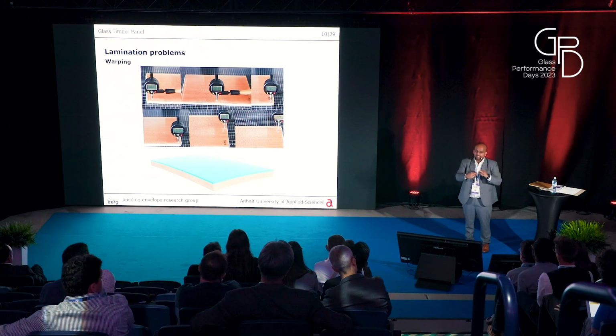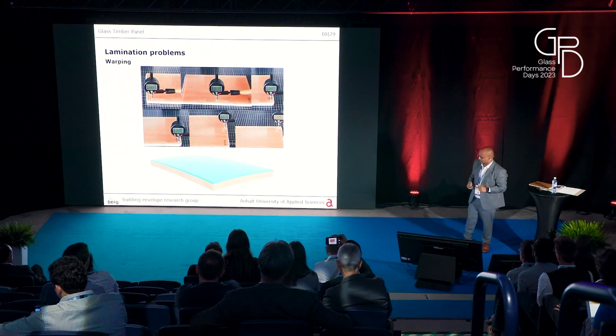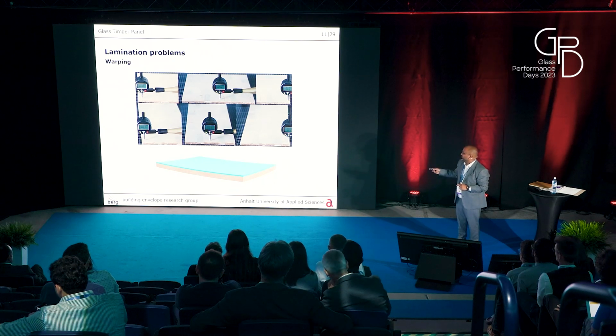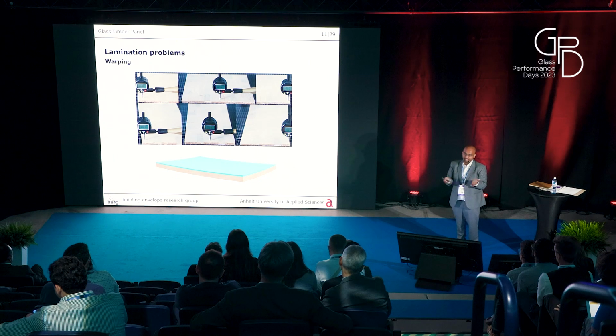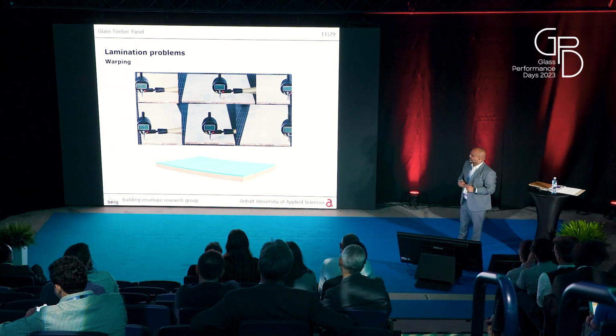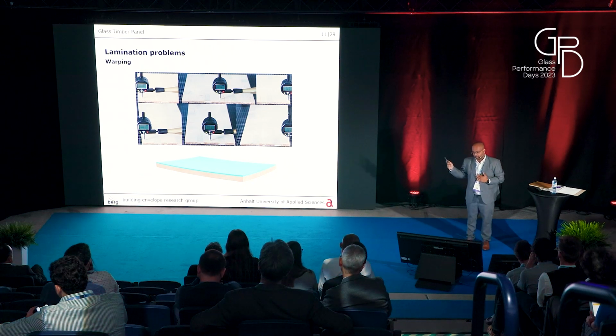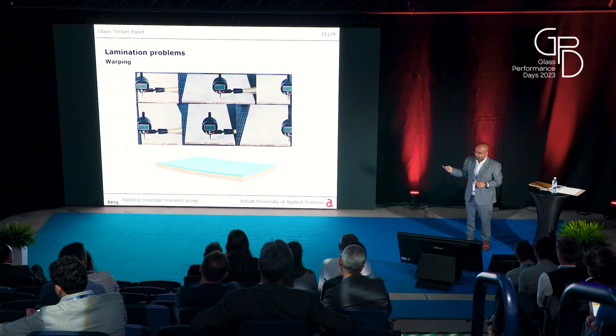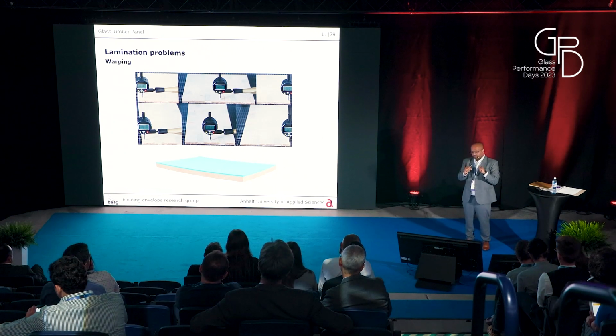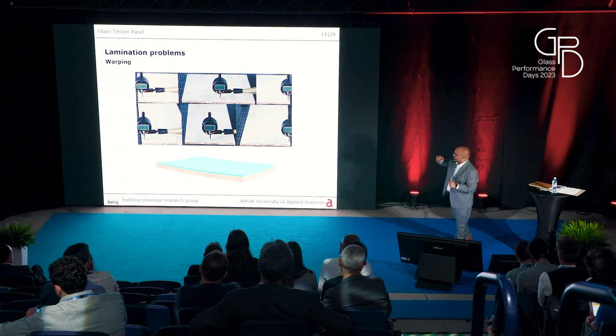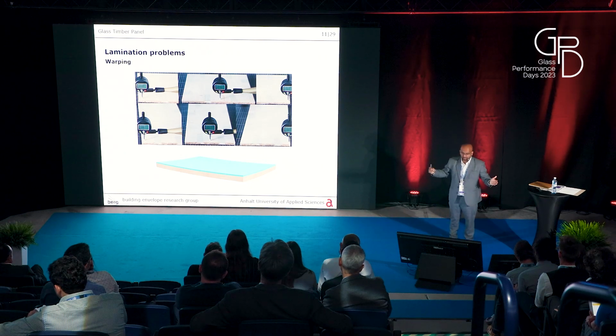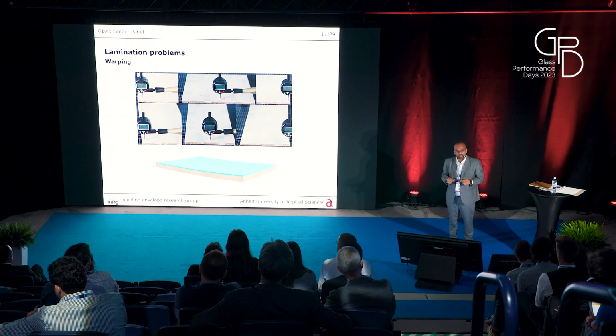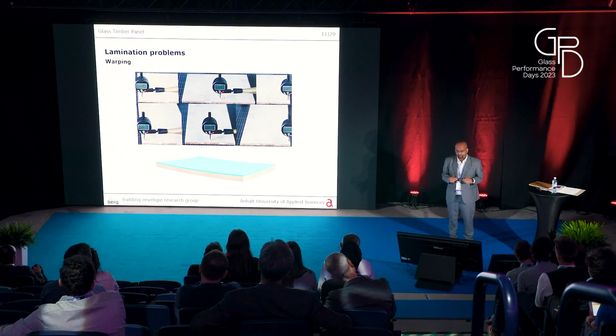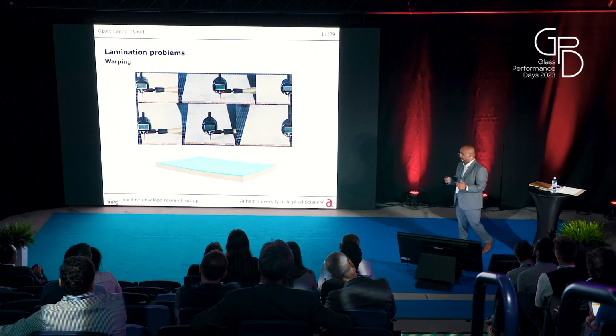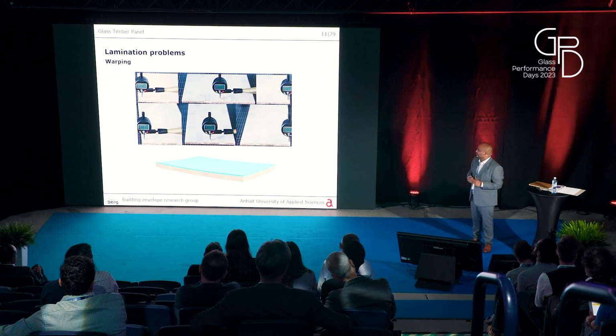And in the center, the foil is still very thick and developing stresses on the glass and making it break. And similarly, in this case, the wood actually bent, losing its moisture, and causing the whole sample to break. The problem with this is all the samples were 20 by 30 centimeters, and at that level, for 20 centimeters, it was 0.5 millimeter, so a 0.5 millimeter curvature. So when we make large scale models of 1 meter size, we would have a warping of 2.5 millimeter, which would be hard for manufacturing of joints or any furniture. So how did we solve this?